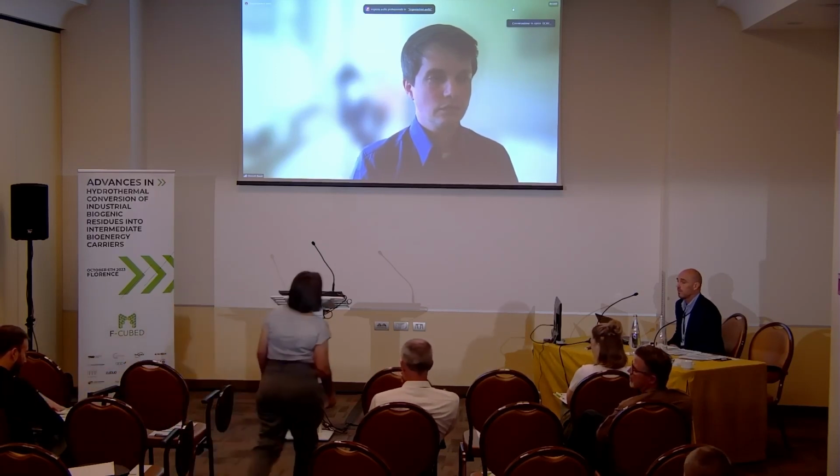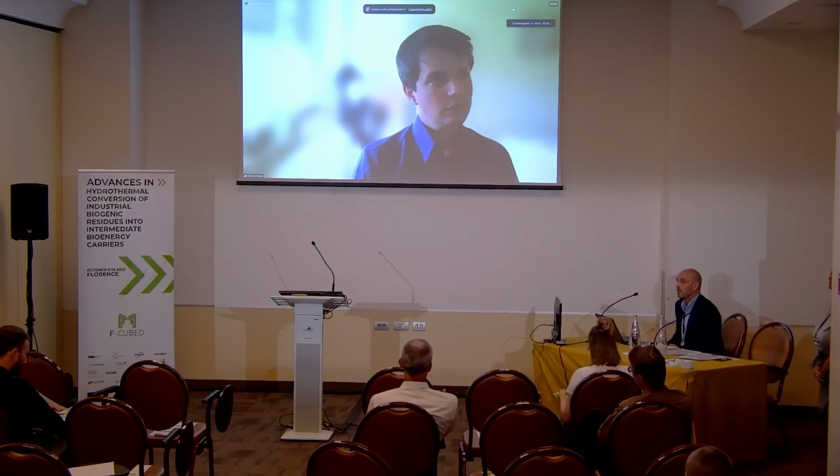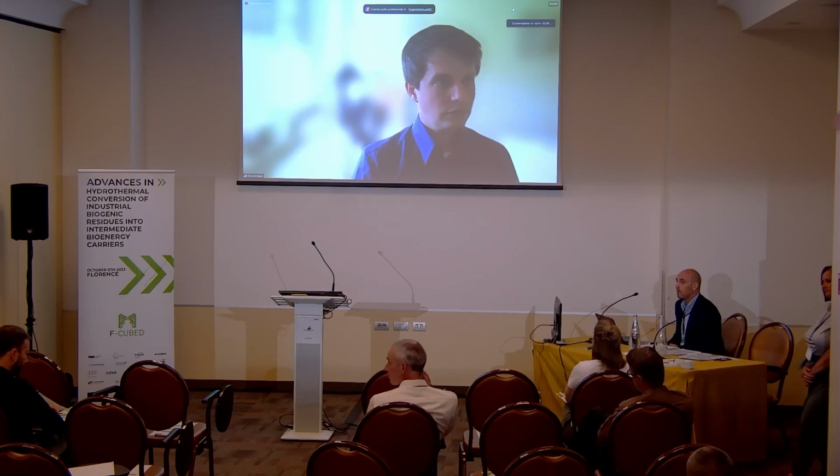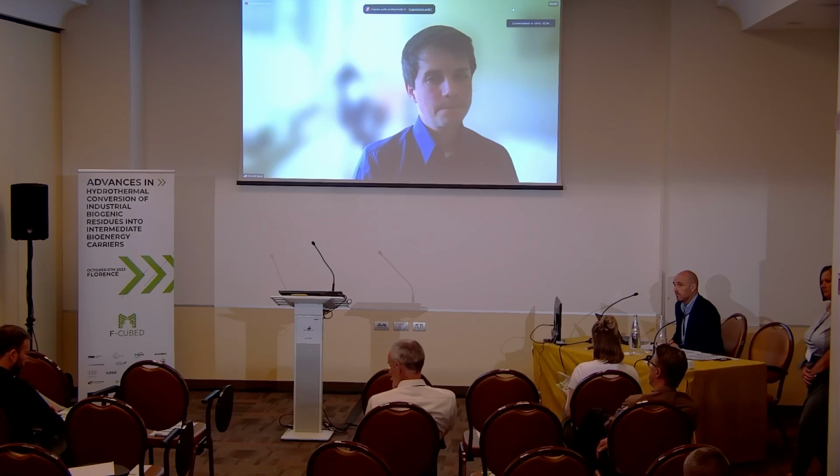Hi, thanks for your presentation. I have a question regarding the phosphorus content in the solid sludge product, because we care a lot about the phosphorus content in the product in the steel making process, because phosphorus is a harmful element in steel making. To remove the phosphorus from steel, we need to add a lot of calcium oxide into the slag, which means we will have a lot of byproduct produced during the smelting process.